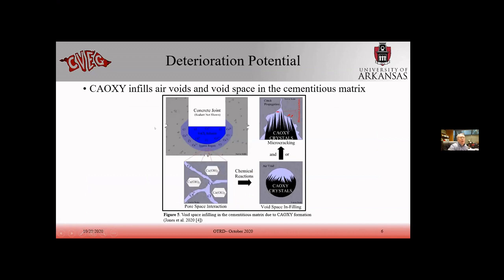All right, so here's the bottom of our concrete joint. Here are our de-icing salts, and you can see they can get some pore space interaction between the chloride ions and calcium ions. We have our calcium hydroxide. If we're in an air void, that's great because the calcium oxychloride can form within an air void. But if it's not in an air void, it can form within pores or within the concrete and cause some cracking, and that cracking can propagate and lead to additional deterioration.